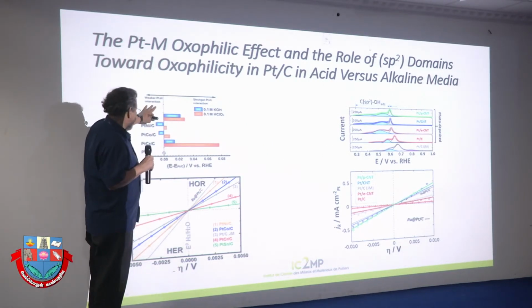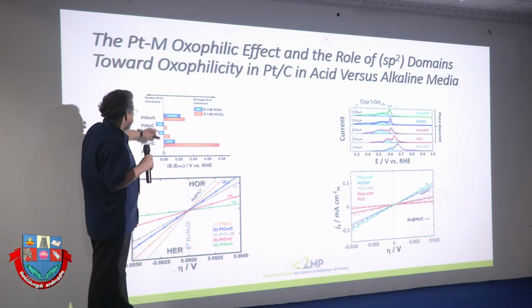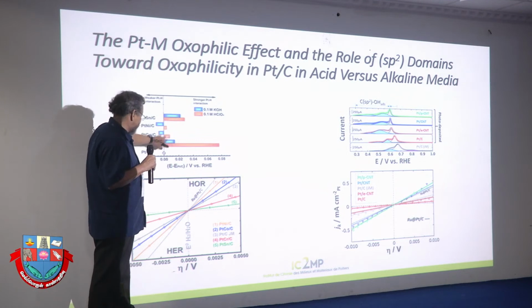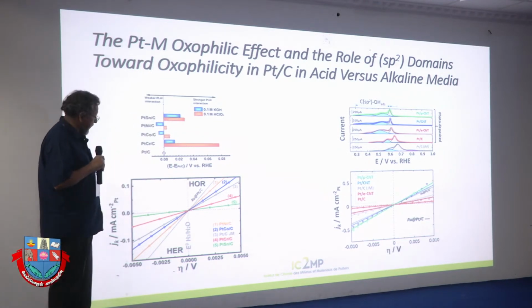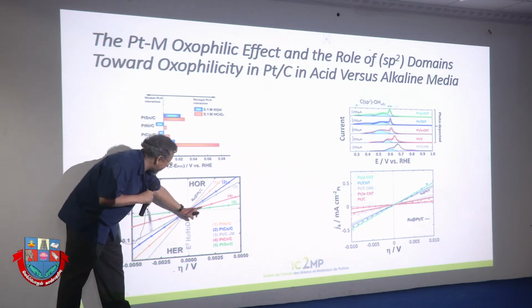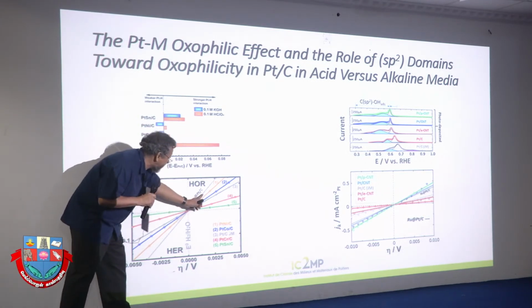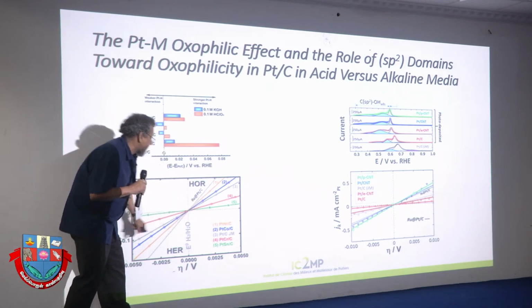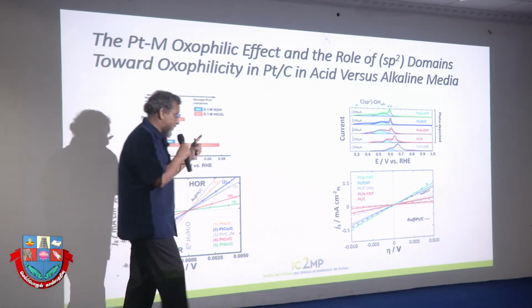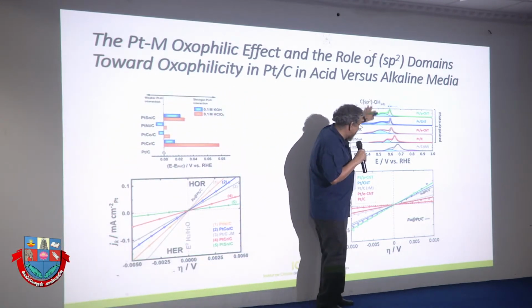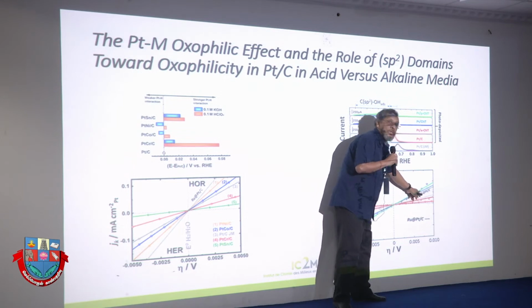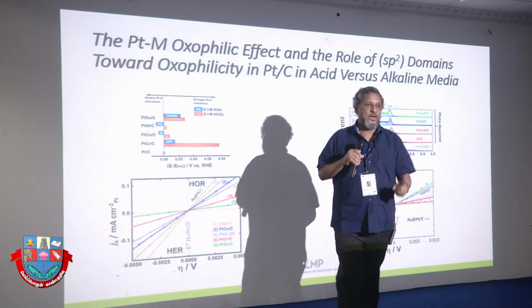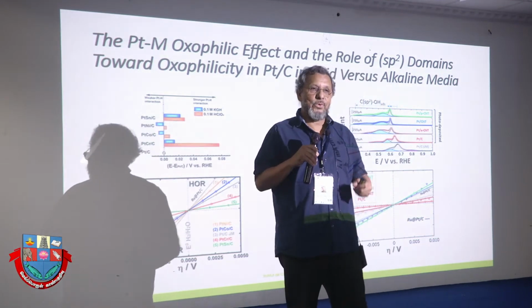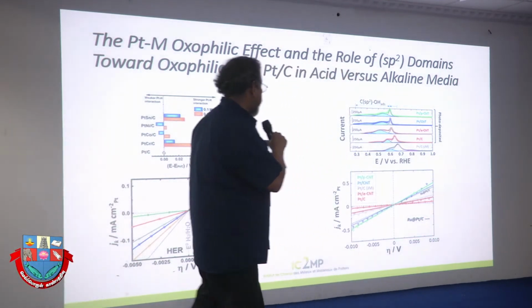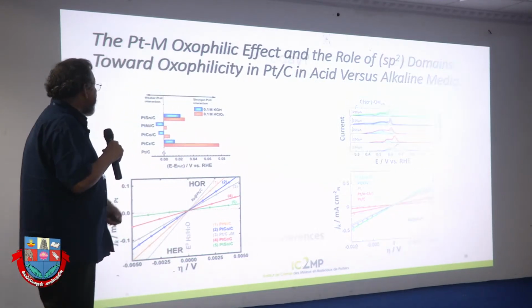So here, we estimated the strengths between the hydrogen and the different catalysts. One is negative, one is positive, and this is observed here in the microdomain. You see that the platinum-ruthenium that I showed before is a little bit more important than the other one. But now when I compare with the non-precious metal, that means the carbon sp2 domain, this guy here below. And that is an interesting view because I can modify platinum without using a very expensive partner like sp2 carbon. Okay, I think that is almost my last slide.